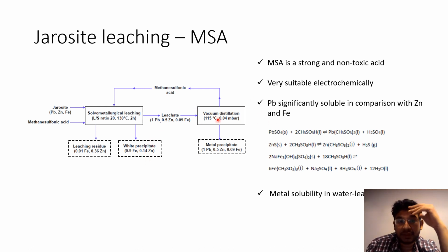The most interesting thing happens here. So you take the precipitate, you take the leachate, which is almost all of the lead present in the waste has been dissolved selectively, and 50% of zinc, and almost nothing in terms of iron. You take the leachate, and you can have a sort of vacuum distillation process in which you can have the methane sulfonic acid recovered back from this leachate. So the methane sulfonic acid neatly goes back. You can't do it for so many inorganic acids. Okay. Once you do that, you form sort of a collective precipitate, and this precipitate can be processed further.